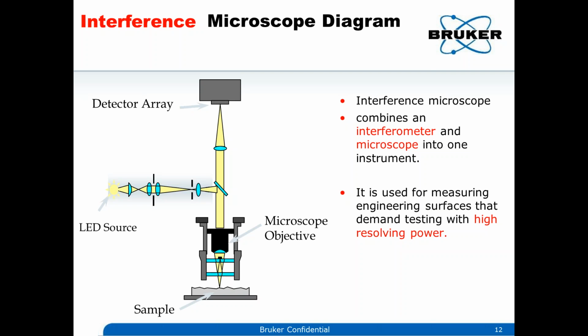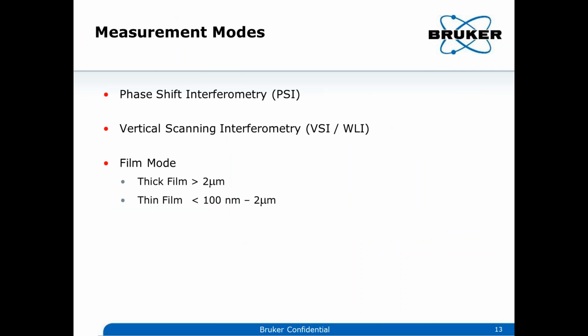So the Z resolution is not limited by the objective. It's very high. It's about 3 nanometers in Z resolution. There are 3 major modes in a white light interferometric technique. One of them is called Phase Shifting Interferometry, or PSI. This technique can be used for ultra high resolution imaging, sub-nanometer Z resolution, for very, very smooth surfaces like your silicon wafers or your mirrors, or very fine thin film coatings, those kinds of applications.